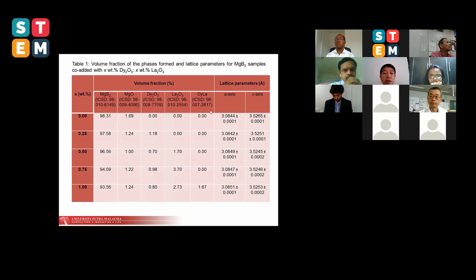Here, this is the table that we calculated. For example, here the volume fraction: we have MgB2, MgO here, that's the unreacted dysprosium oxide, and that is the unreacted lanthanum oxide, and this is the dysprosium lanthanum phase. The dysprosium lanthanum phase only appears for high addition levels. So the rest of the byproducts or the unreacted products are dysprosium oxide and also lanthanum oxide. And we also noticed that the MgB2 phase actually decreases slightly.